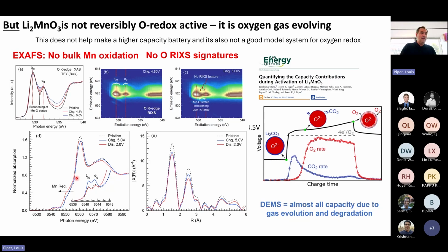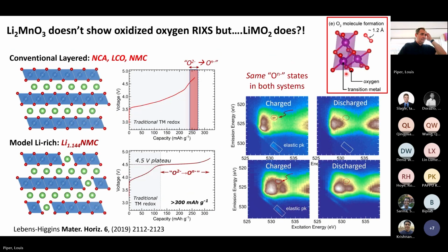And that meant on subsequent cycles, you're going on a 3+ to 4+ conventional redox after you've done that first cycle. But you only see noticeable amounts when you've got a large ratio between your surface region and your bulk. So small particles, you see this; larger particles, you don't see this. So this was work where we said, well, we wanted to understand more of those mechanisms. Let's use our model system of the endpoint, and then we realized the endpoint was not actually a good candidate for describing oxygen redox.